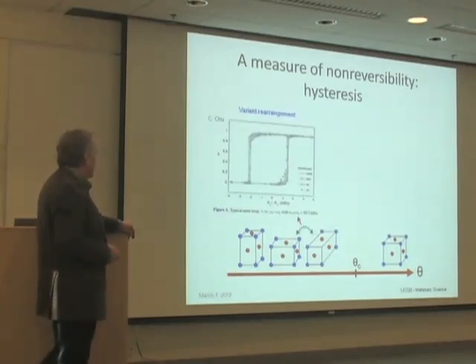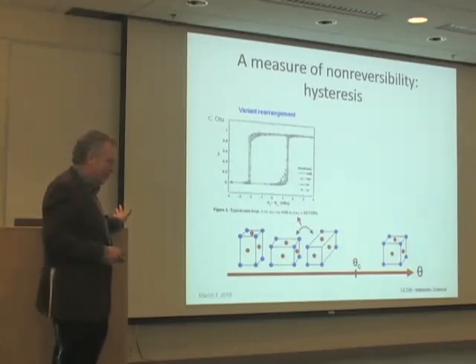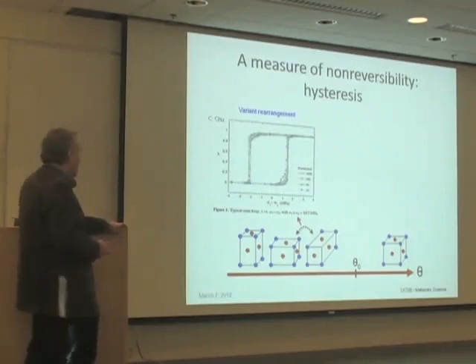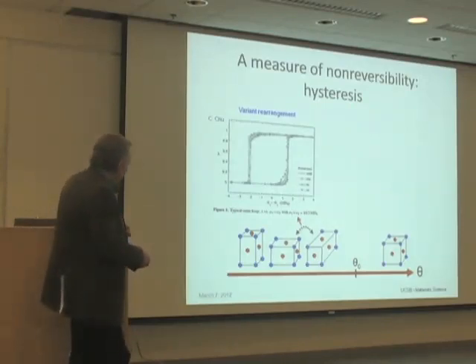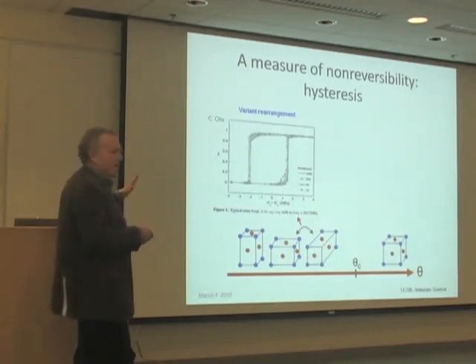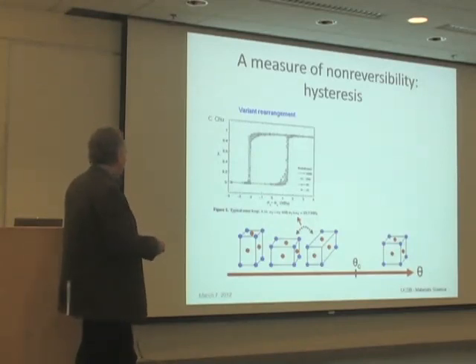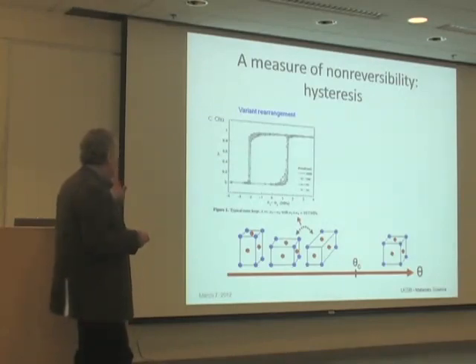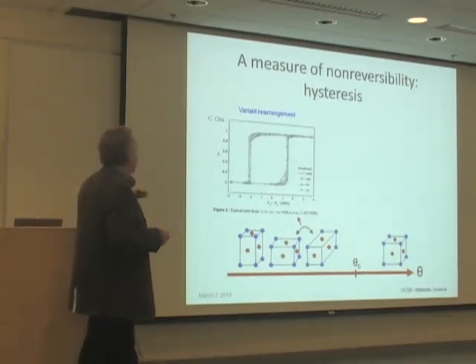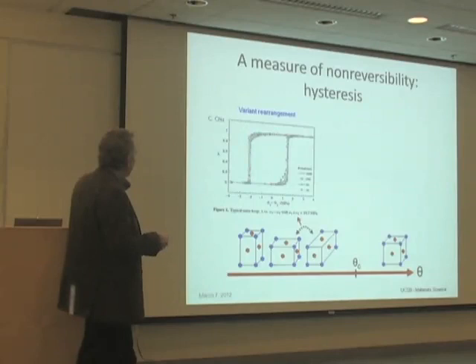And we're going to talk about the reversibility of phase transformations. And the measure of reversibility will be this hysteresis. So first, let me discuss the hysteresis in transforming from this variant of martensite to this variant of martensite. And there's an experimental measurement. I won't describe how it was done. It was done with stress. This is some kind of measure of the stress. It was done with a particular design of a loading device that was designed to give a nice square hysteresis loop, and so that's the hysteresis loop. And this is the volume fraction of this variant versus this variant. It goes from 0 to 1.